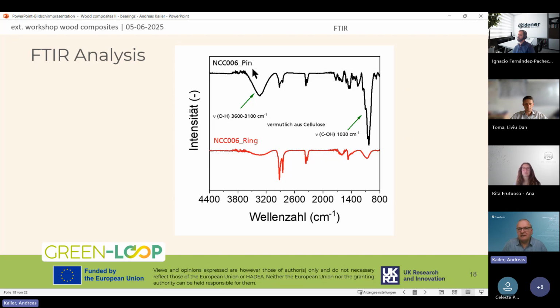So on the pin, you can see the FTIR spectrum of the wood composite, which is in black, and on the steel ring in the wear surface, we can see material transfer. So there has been a slight material transfer from the wood composite onto the steel surface, on a small scale, and this enables the low friction as we propose at this moment.